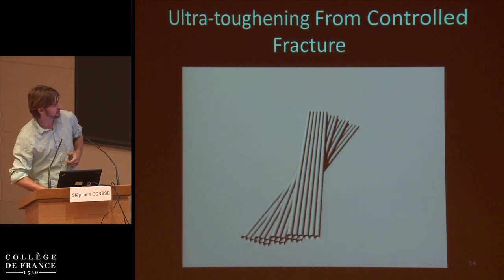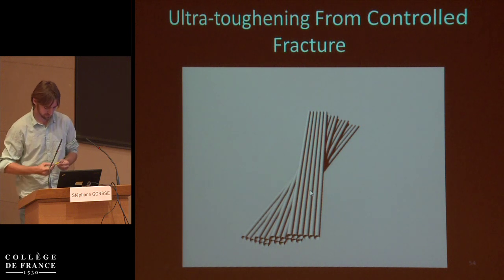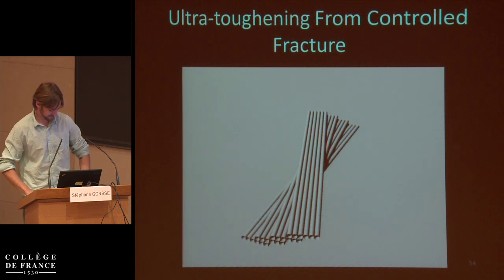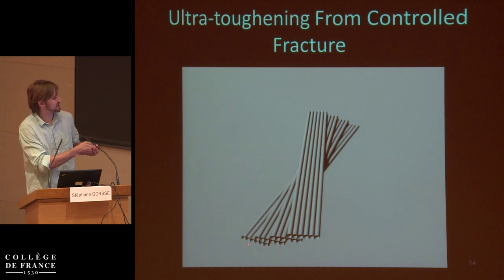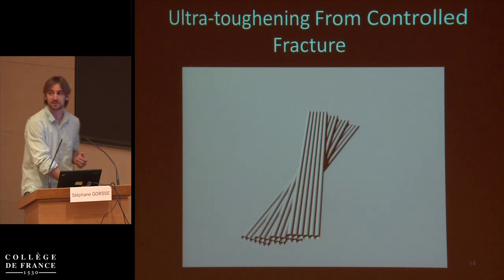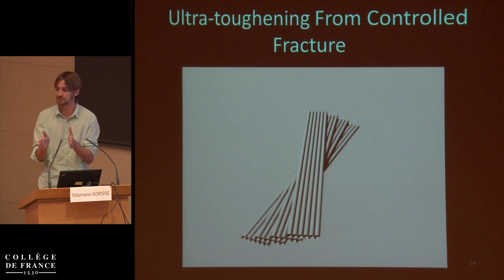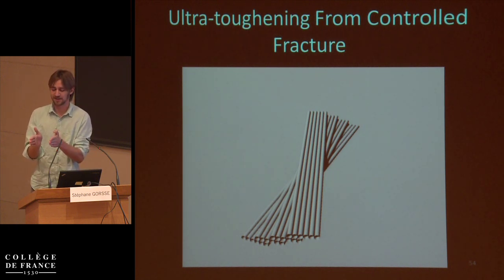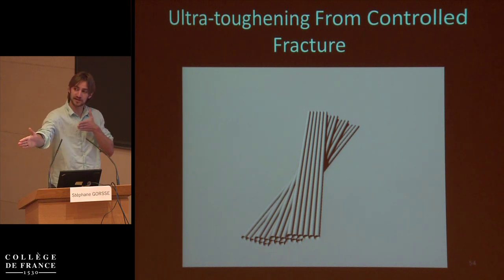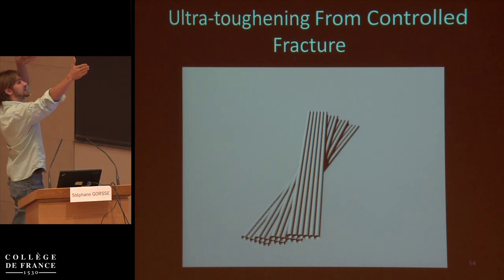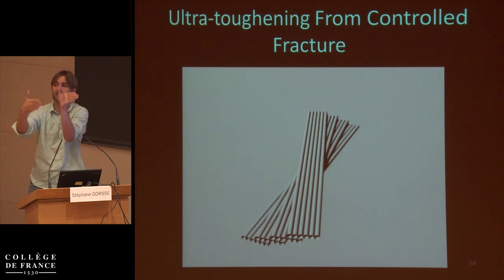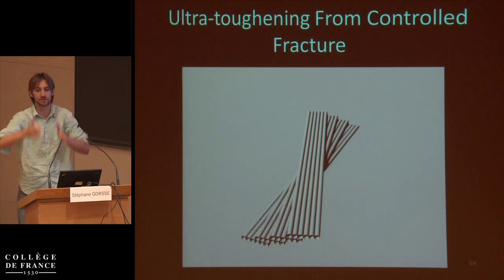So if we consider a fracture that initiated from this one, it doesn't have to match up and come over to this guy. It would just, as soon as it crosses through this delamination zone and then finds this hole here, it's going to take this one. So what that means is that you have a fracture branching mechanism. And so to use my hands, which seems to be a theme of this symposium, if I'm a fracture and I'm growing this way, and the longer I get this way, instead of me twisting around like this, it's easier just to split and become two fractures now, propagating through the thickness of the material.